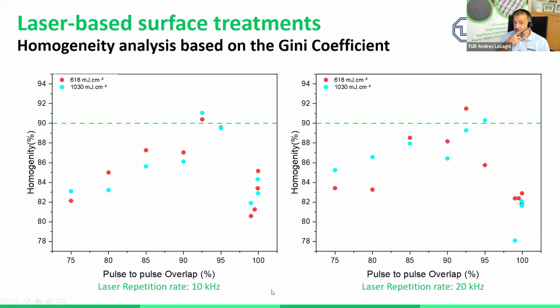In our proposal, we define that our target is to get an homogeneity of 90%. This is our target in the process to assure a high performance of our textures everywhere on the surface where we create our periodic structures. And you can see that for some conditions, we can reach that. This does not mean that a structure with a higher homogeneity will also have a high performance. So at the end, it's a question of speed, of energy. This is going to be evaluated if we can make, for example, anti-corrosion property with 70% of homogeneity, but if we use 50% less energy, of course, that's what we are going to take. But this is, for us, a parameter determining the quality of our parts.